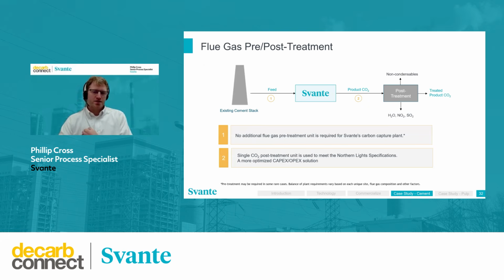For the cement plant used for this study, we were able to take flue gas directly from the stack and send it to our battery limit. We recovered a little bit of waste heat, cooled it to the appropriate temperature, and then sent it into the carbon capture plant. The CO2 product coming off the Svante system went into a single post-treatment unit and was able to meet the Northern Lights specs. So what this highlights is our robustness to process contaminants, and also, as Lionel mentioned, high CO2 purity coming out. We're able to meet specs with single post-treatment options. Next slide, please.